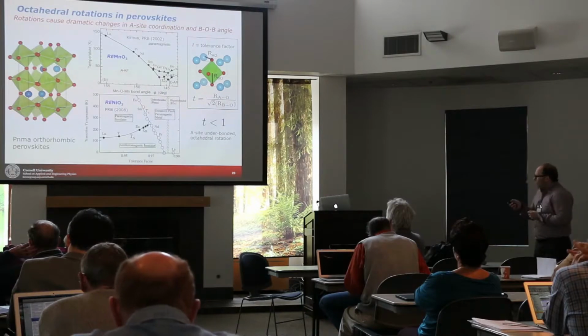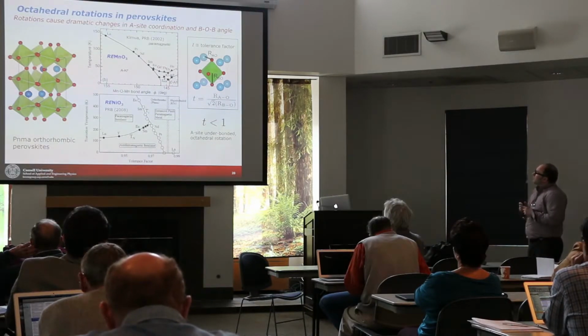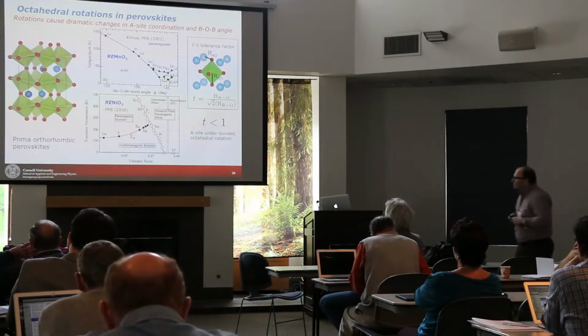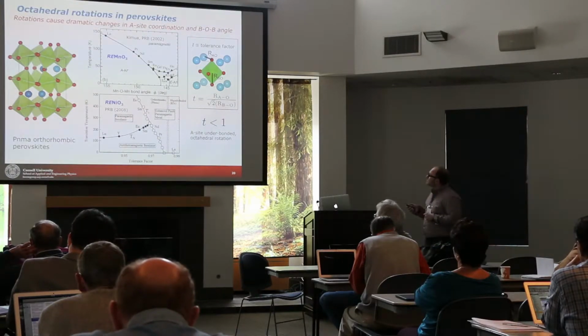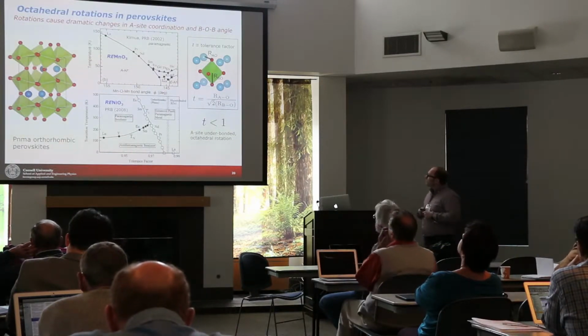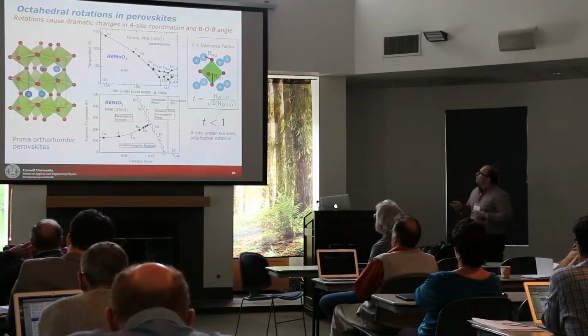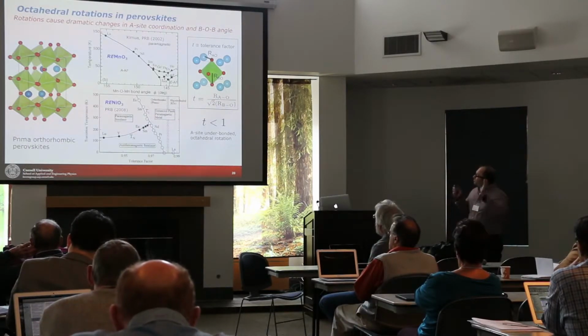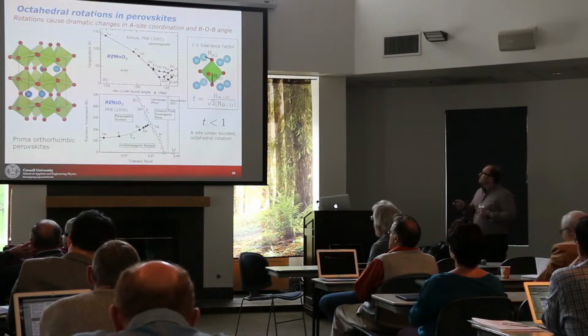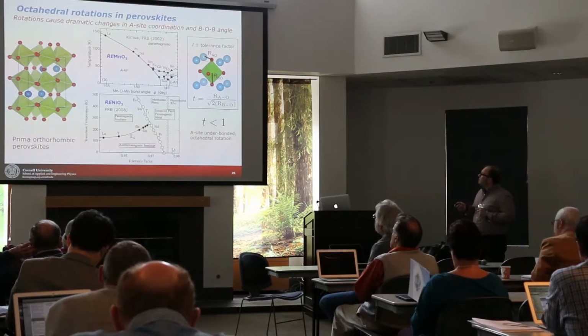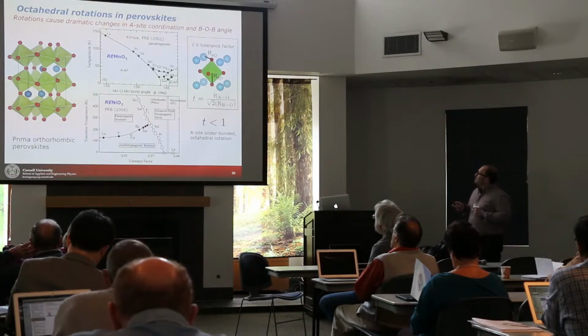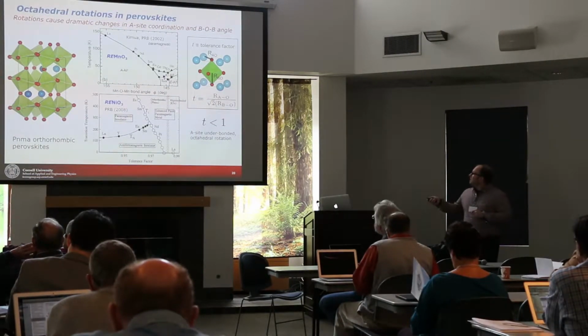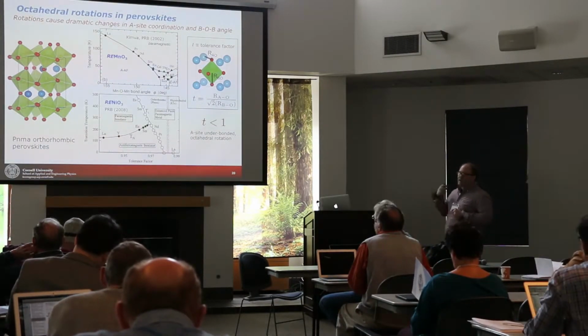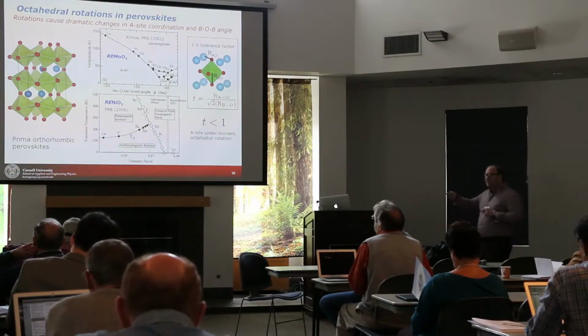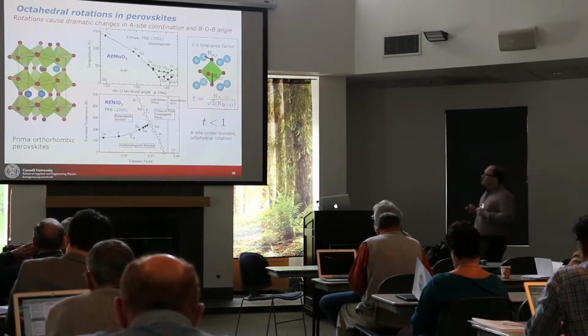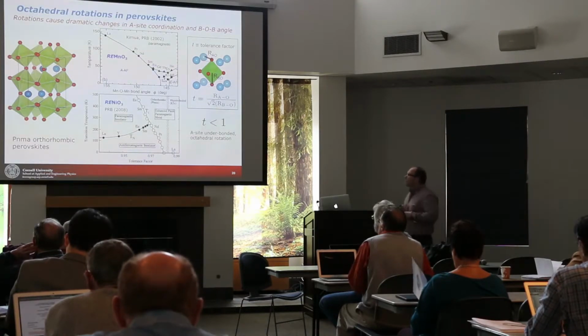Here I'm just showing you 2 phase diagrams of 2 examples. I can show you for just about every transition metal oxide a diagram like this. This is a rare-earth manganite, this is a rare-earth nickelate from the bottom. What we're seeing here is temperature versus some parameter, which I'll mention in just a bit. The dots refer to different compounds, from lanthanum all the way down to holmium in this case. These are all 3+ cations, and these are all 3+ cations. These are isovalent substitutions.